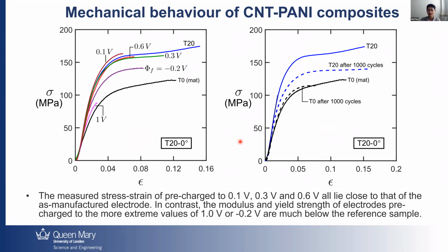How about the mechanical behavior after that pre-charge? We have seen that if we charge it in a kind of safe operational window, which is between 0 voltage to 0.6, we have introduced very limited effect on the mechanical behaviors. However, if we charge it in 1 volt or negative 0.2 volt, there was a significant change of the PANI behaviors. And that mainly correlates with the change of the microstructures and the PANI content.